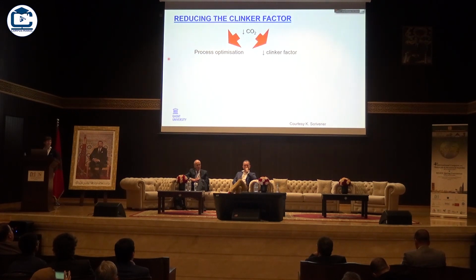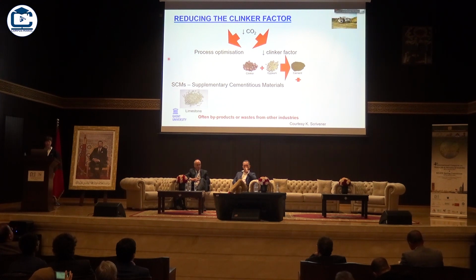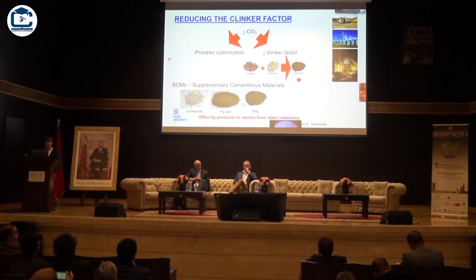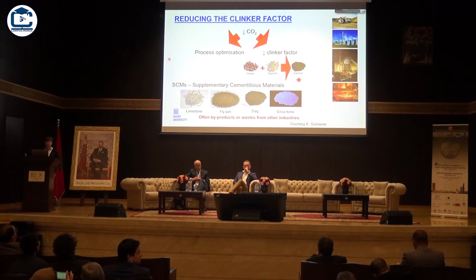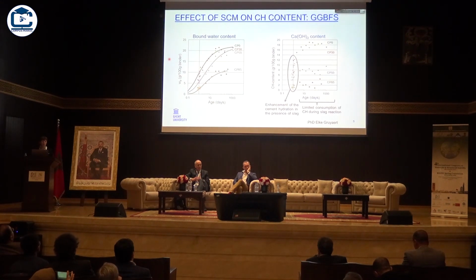You might recognize these slides, which I borrowed kindly from Karen Scrivener, because indeed we want to move to more substitution of clinker by supplementary cementitious materials. And the ones that are currently in use are indeed limestone, fly ashes, slag, silica fume, natural pozzolans, and more also those calcined clays, which you already heard about. Now, there is one thing, indeed, if we change the composition of the Portland cement and we start to introduce more supplementary cementitious materials, that we actually change the composition of the hydrates, and that, well, importantly, we change the amount of Portlandite in the composition.